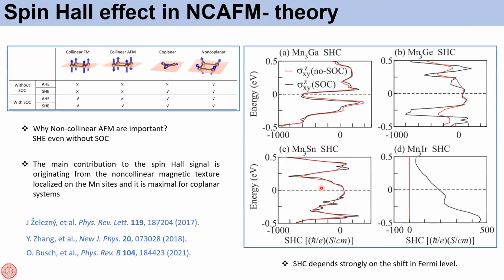But we are interested first of all in the normal spin Hall effect, which was calculated. There was a theory paper back in 2017 where they calculated the spin Hall effect in several non-collinear antiferromagnets, including Mn3Sn, and found that there is a substantial spin Hall effect in this material, which is independent of spin-orbit coupling, but appears because of the magnetic texture in this material.